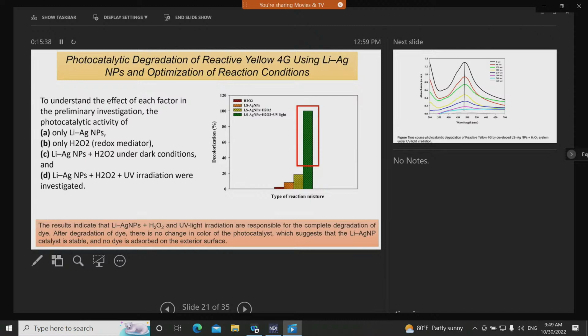And after the degradation of dye, there is no change in the color of the photocatalyst, which suggests that the LiAgNPs catalyst is stable and no dye is adsorbed on the exterior surface compared to the other factors.